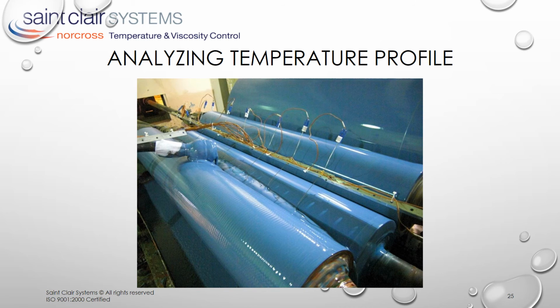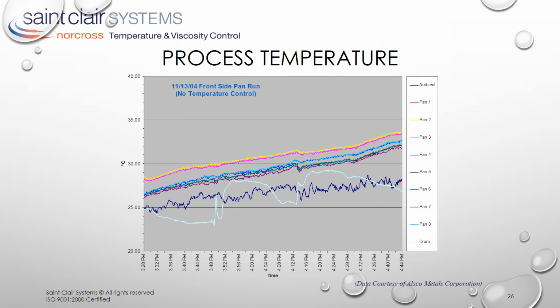Analysis of such a system requires a different approach to measurement, as shown here, where we can see the probes of the data collection system in place across the nip. This is the last opportunity to measure coating temperature prior to application and allows us to identify temperature variations from edge to edge and over time, or head to tail on the coil, which results in variation in DFT. We refer to this as the thermal profile of the nip. The heating phenomenon is clearly demonstrated in this plot, which shows the temperature profile of a roll coating system without temperature control over an hour's time.